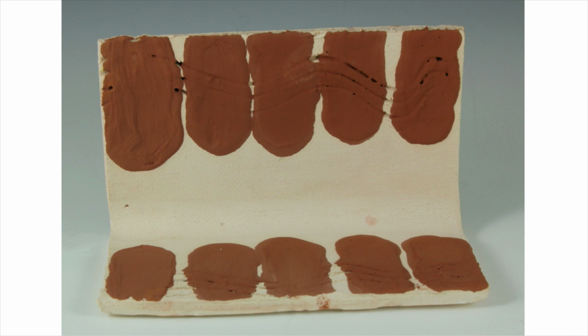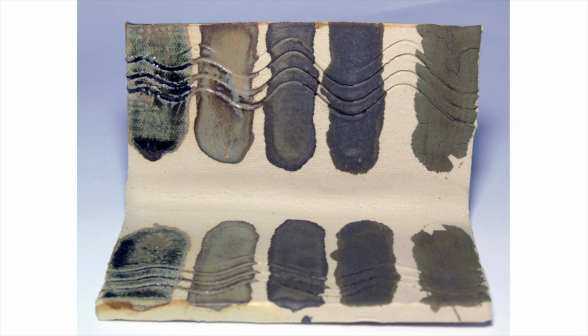So what I did was take 500 grams of the wet batch of glaze, weigh that out, then add 50 grams of dry EPK to that. The first stripe is just the wet batch of glaze, then 50 grams, which is 10% since it was a 500 gram batch, then another 10%, another 10%, another 10%. Then I fired the tile.